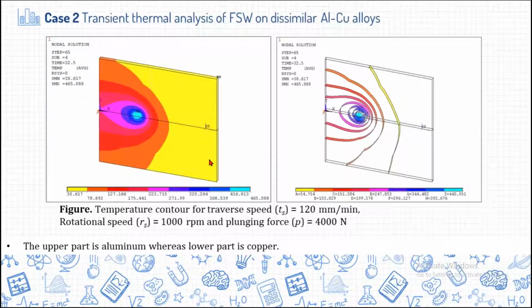And we observed the temperature for these particular process parameters: 120 millimeter per minute welding speed, 4000 newton plunging force and 1000 rpm. We got around 465 degrees centigrade, which is within the range. This is the thermal contour from the simulation.